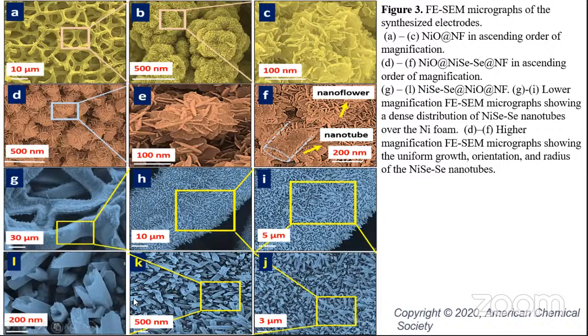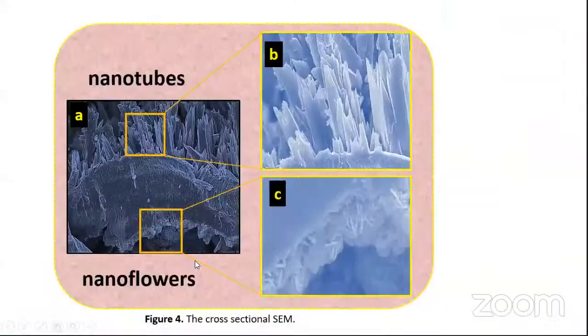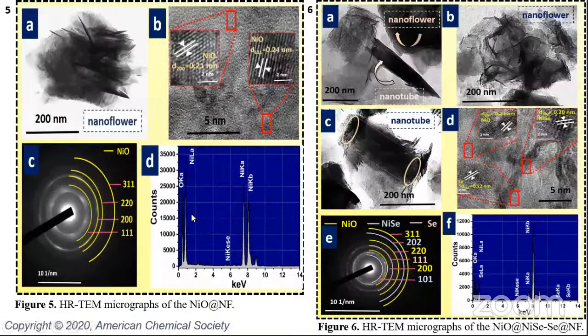To confirm the nanotubular structure which has been grown on nickel oxide nanoflowers, we also took the cross-sectional FESEM analysis. Here you can see the nanoflower as well as nanotube structures both. Now, coming to the HRTEM micrograph, again the morphology of the pure sample, the nanoflower structure, was confirmed, and the presence of nickel oxide planes was also confirmed from the d-spacing analysis. Then the EDX analysis also reflected similar results.